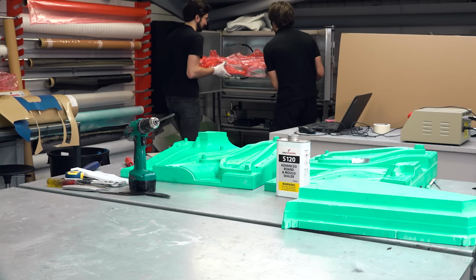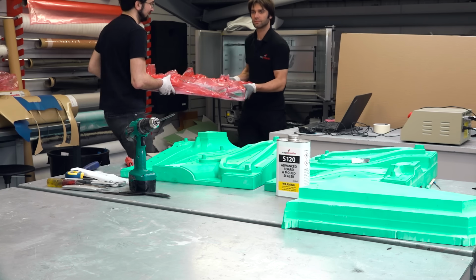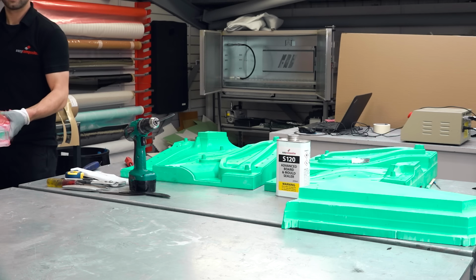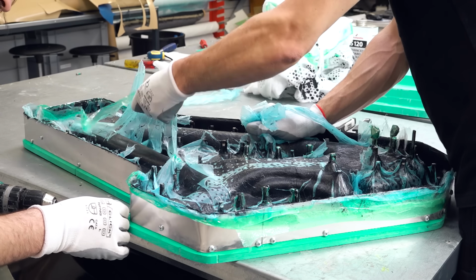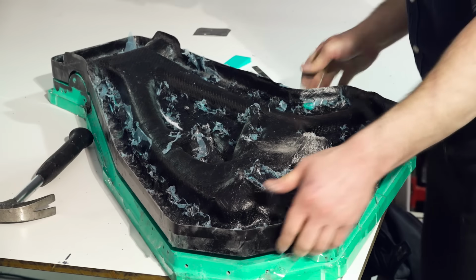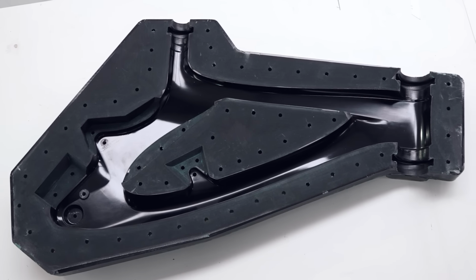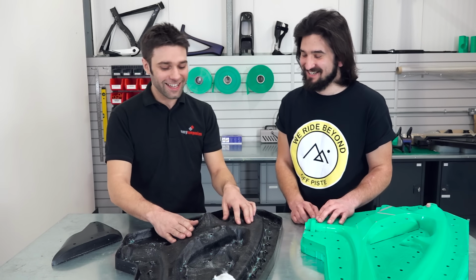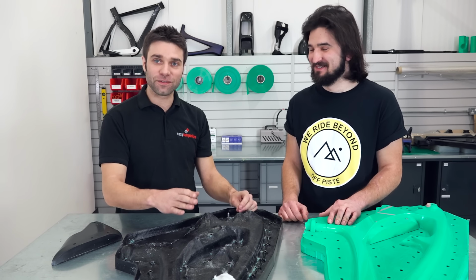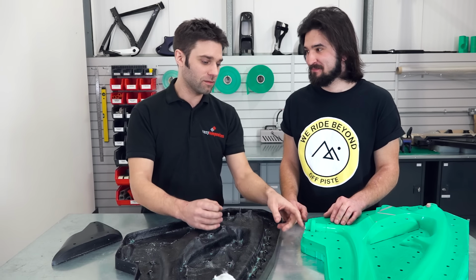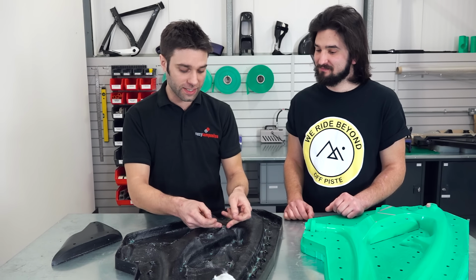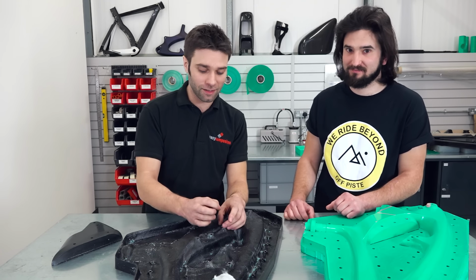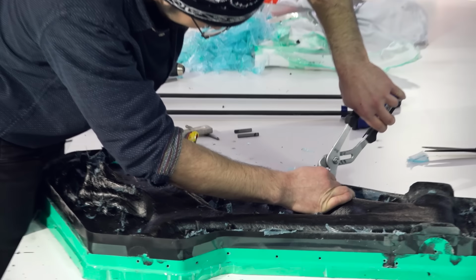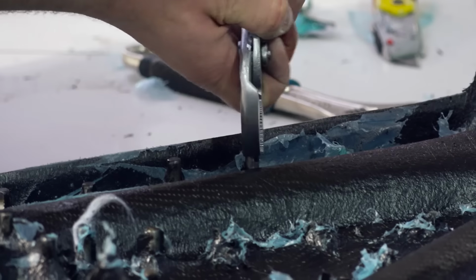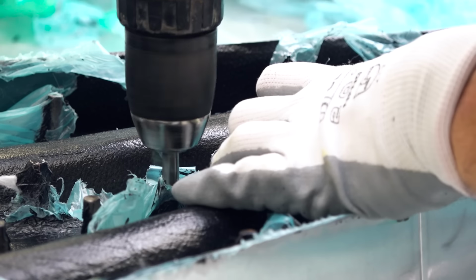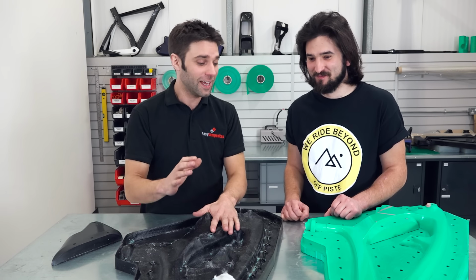So once it was all laid up, that's been cured. So it was done a low temperature initial cure. Yeah, low temperature initial cure, which was slightly longer. Then it was taken off the tool after a good fight with all those pins. Yes. Extracting the pins from this, if you imagine the mold, the pins coming out of here through this section, they were completely parallel pins. So actually drawing them out is quite difficult. We opted for a trick of using a cordless drill to actually spin them out, and that worked reasonably. It did work quite well.